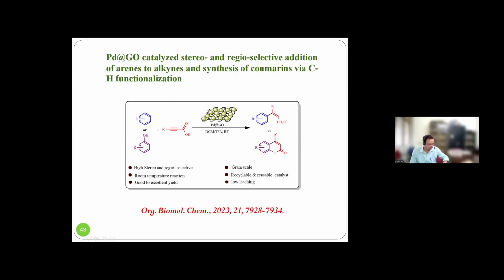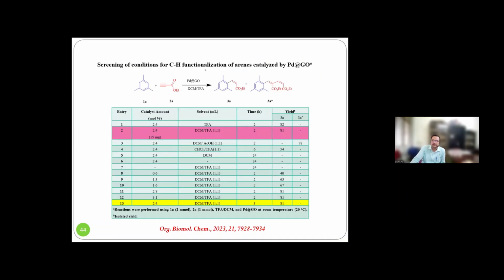Next is the palladium GO catalyst for the stereo and regio selective addition of arenes. Actually, this is one of the named reactions, called CH activation reaction. So here what we did actually, we dope palladium on the GO surface, and then we use alkyne for CH activation reaction. We successfully prepared this alkene, and the reaction condition is 2.4 mole percent of the catalyst in DCM TFA 1:1 ratio for 3 hours. It gives 81% yield.